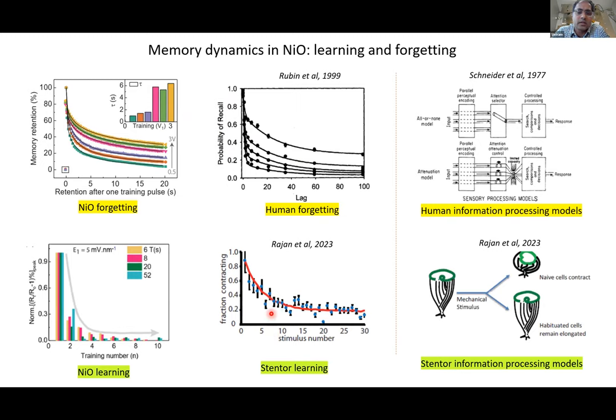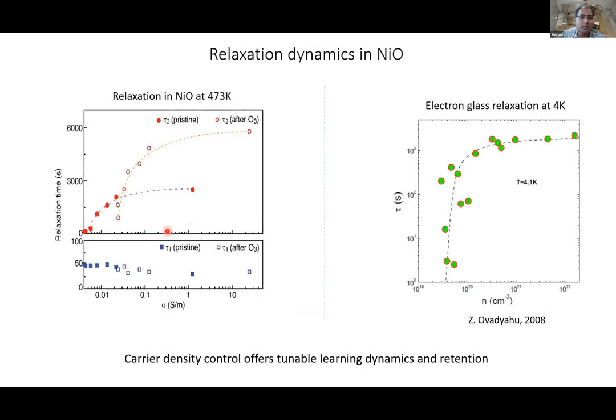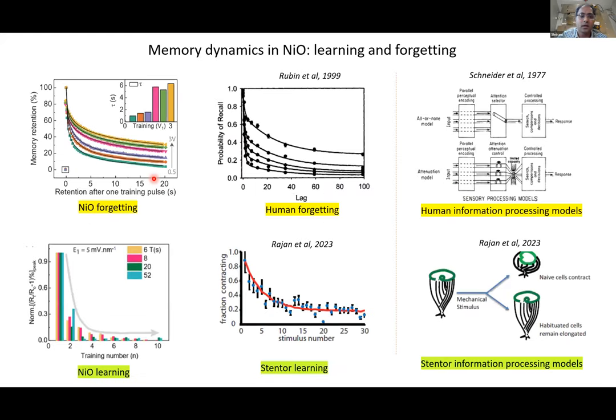So this is Stentor, which is a simple single cellular organism where people have studied learning and forgetting. And you can mimic similar results as a function of training. So the main mechanism here that enables this type of emulation is defects that are metastable. They can spontaneously relax back when the stimulus is removed. This doesn't happen for all nickel oxide, by the way. In this plot, you see that the time scales are very sensitive to the initial conductivity or the non-stoichiometry. So we don't fully understand this for sure.